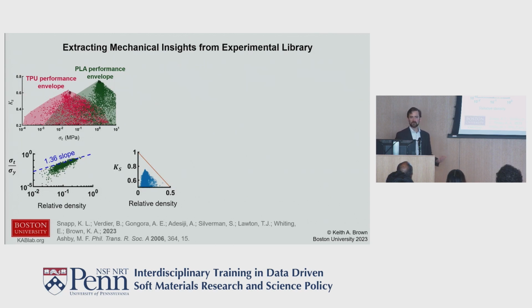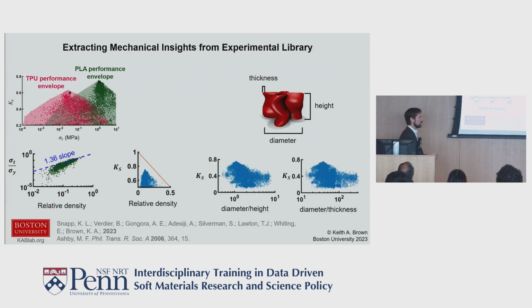And we can look more generally at how people tend to think about these mechanical structures. In the world of cylindrical shells, we think about properties like the thickness, the height, and the diameter of these components, and whether we can just look at how these properties matter. We can look at our 10,000+ data points and see the efficiency versus some aspect ratios, for example, how wide the part is relative to how tall it is, or how wide it is relative to its thickness. In both cases, we have optima. We're digging into these increasingly, but in the cylindrical buckling world, it's known that there are competing ideas of trying to manage the buckling that can show up by allowing it to have interesting reentrant properties. And allowing us to tune these values lets us find interesting locations here.